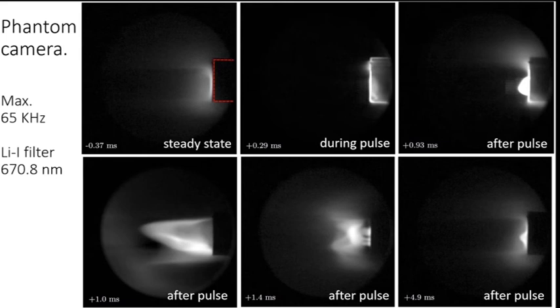which I thought was very interesting because you cannot evaporate an infinite amount of liquid metal, because it will interfere with your fuel mixture. So there are significant limitations to what you can evaporate, and we should be careful. Even though we can withstand pulses, which is great, we should still be careful what we load this component to.